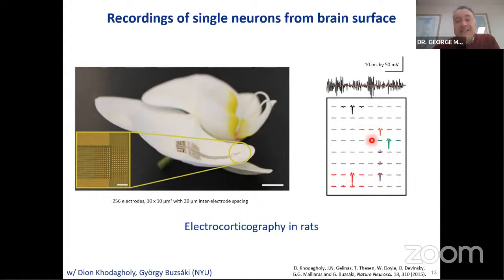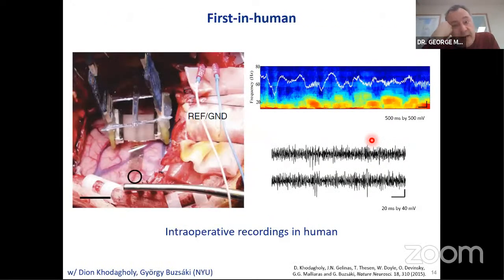So in a sense, you reach the ultimate spatial resolution. You reach the limit where you can pick up now individual neurons without penetrating the brain, by just sitting at its surface. This is very powerful because you go from centimeter spatial resolution down to single neurons. You can now latch into a single neuron and follow its chatter over time. It's a great tool for neuroscience. But it's more than that. It's also a great tool for the clinic because it allows you very high resolution recordings. And as a result of this compelling advantage, the fact that you go from centimeters to tens of microns in spatial resolution, this is now used in the clinic.